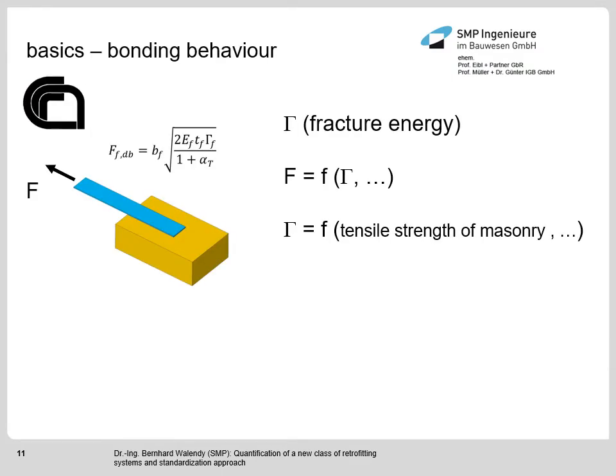There are some regulations on national level in Europe on how to quantify the reinforcing effect of fiber reinforced polymers for masonry. One of the most prominent ones is the Italian regulation CNR-DT, and here the formula to quantify the maximum force which can be transferred to a fiber reinforced polymer before debonding starts is shown on the upper left corner. As you can see, the maximum force is mainly a function of gamma, which means the fracture energy. And the fracture energy is mainly a function of the tensile strength of the masonry.